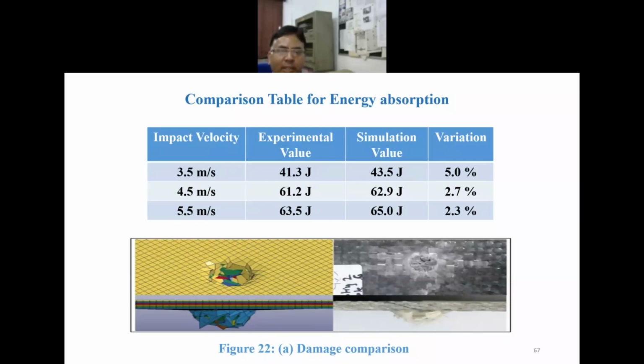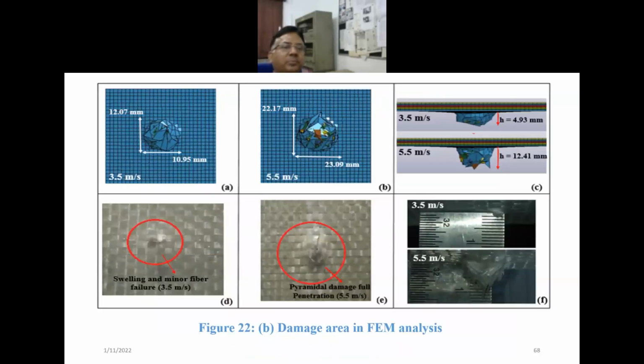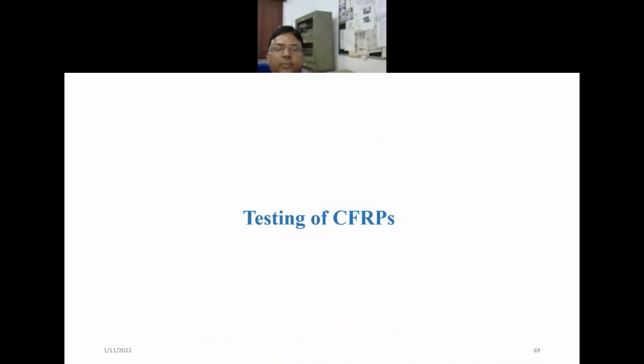So what we are doing, the level of the experimental work in the lab, making the materials, designing and simulating those things, that research quality is showing in the variation here. It is 5% or less than 5%. So this is showing the good quality of the research. Now the damage area in FEM analysis, we can use this, and we can see these materials in our machines. There we also have the SEM facility, scanning electron microscopy. There you can see the damage and the fiber breakage.